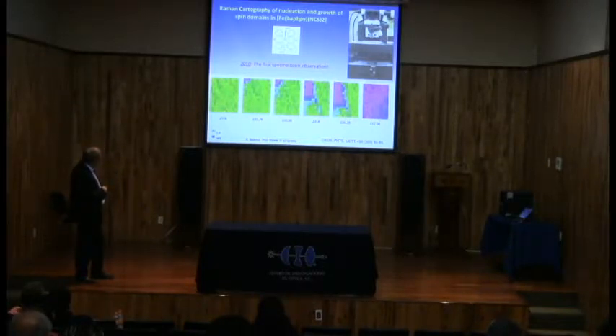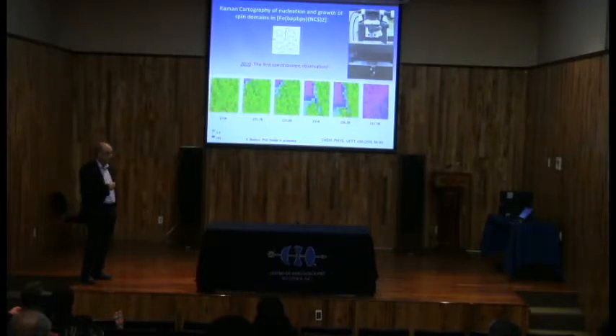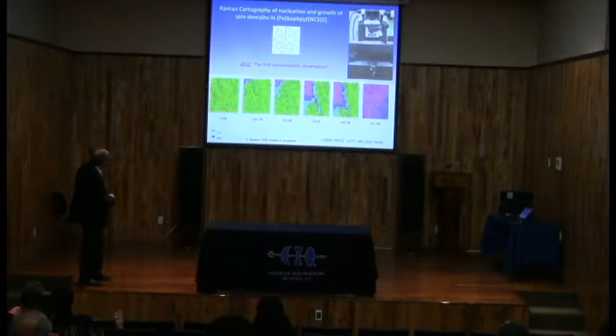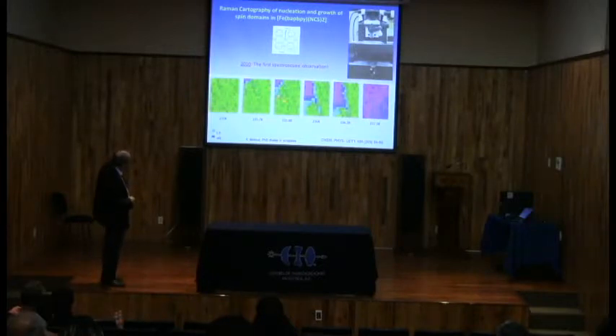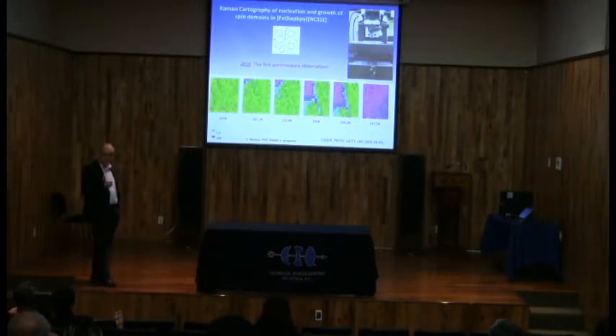We image the crystal by Raman spectroscopy as a function of temperature in the region where you have the switching. What you can see here is the system at 235 in the low spin state. When you increase your temperature, you see the appearance of some domains of high spin form. And when you continue heating your system, you see the domains of high spin state increase until total conversion. This is the demonstration by spectroscopy that when you have the temperature switching through the region where the system is switched, the process is a nucleation and growth process.